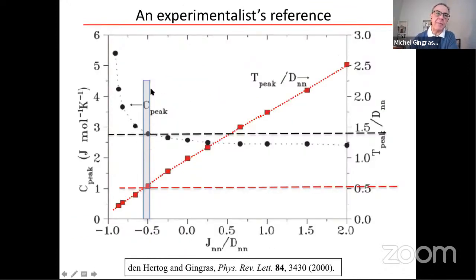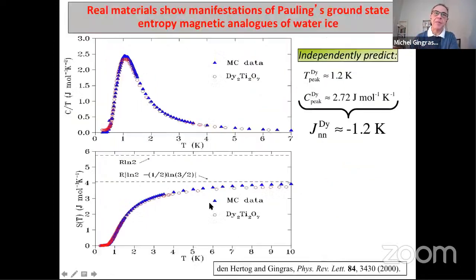And these two quantities, the value of the peak at 2.72 and the temperature at which the peak occurs, since we know D, we know the peak is at 1.2 Kelvin. These two quantities give us the value of J over D. And so we find that it's minus 0.5, plus or minus 5%. Since we know the value of the dipole interactions, we know J by fitting either the peak of the specific heat or the location of the peak. And so this is what it looks like.